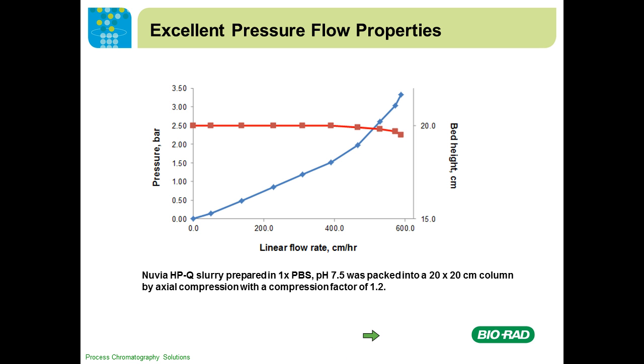And the rigidity was studied in a large-pack column, the 20 by 20 centimeter column. As you can see, between 0 and 400 centimeters per hour, the bed has no compression, and the pressure-flow curve is linear, which indicates that the base bead is very rigid. Even over 400 centimeters per hour, there's only very limited compression.